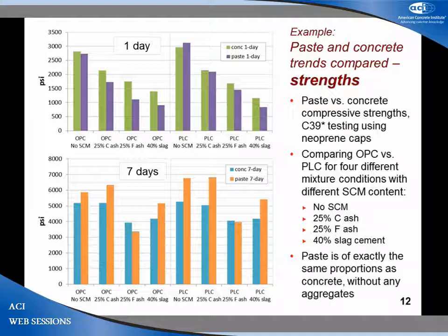As a matter of fact, if you just study the green bars, the concrete, to get your concrete trends, and then you look at the blue bars, the paste strengths, what we typically see, and this is true for setting times as well as strengths, is that the trends are slightly exaggerated in the case of laboratory paste relative to concrete. That's actually a good thing because it's very easy to pick up those trends as you do this work, but the trends tend to be quite consistent and very usable.